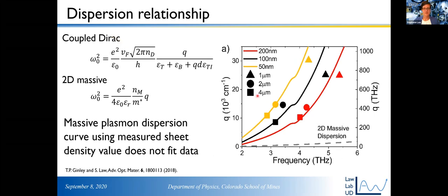So this is the plot that has all the data in it. The symbols are the extracted plasmon peaks. This is where the plasmon modes are experimentally. These curves, the yellow, black, and red curves, are the theoretical dispersion curves for coupled Dirac plasmons shown here.